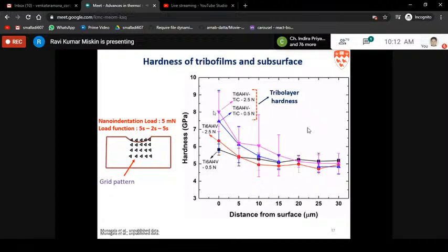So that's how we concluded that when you have tribolayers, you're basically improving the near surface hardness of your material. So as a result, the material that is getting exposed to your actual severe wear conditions is getting less worn out. So even though you have a small material there, you have actually protected the bulk surface. So that's one application we found. Next.